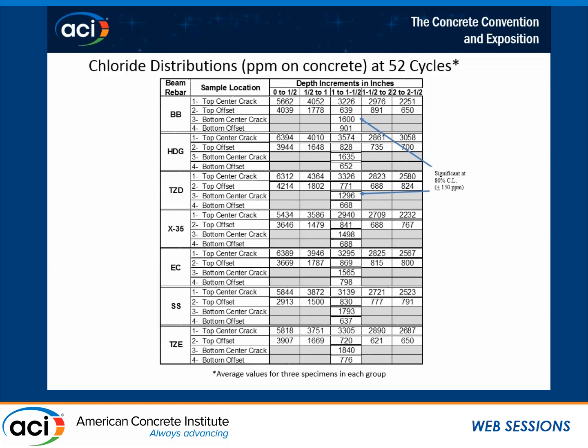This TZD has a very porous coating on the bar. It bonds very well, and you can see there was a little bit, at least to an 80% confidence limit, a reduction in chloride at that level. With more samples, we would expect to see more of an offset, and that actually looked like it might help the crack close up a little bit.